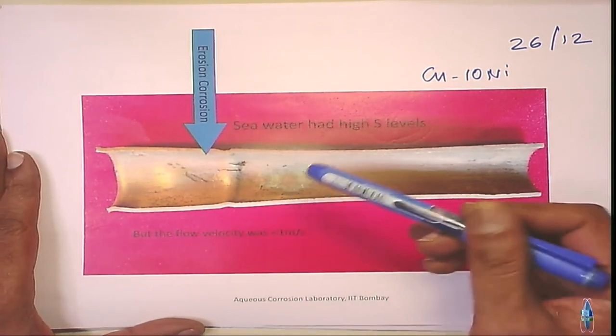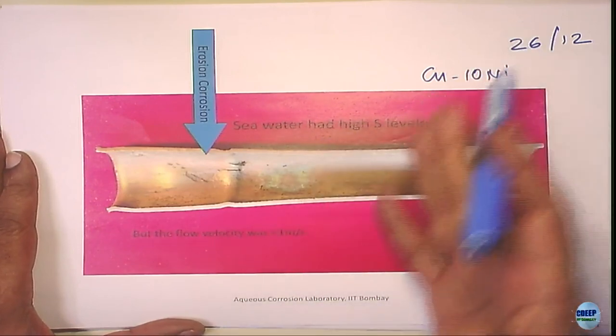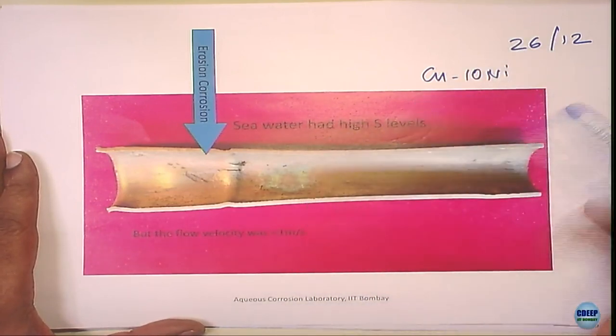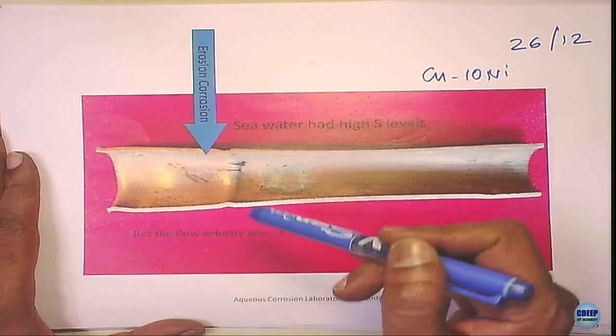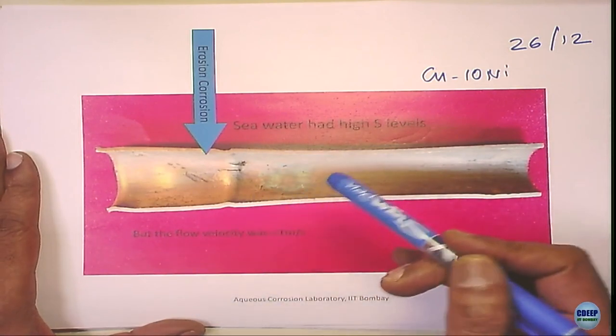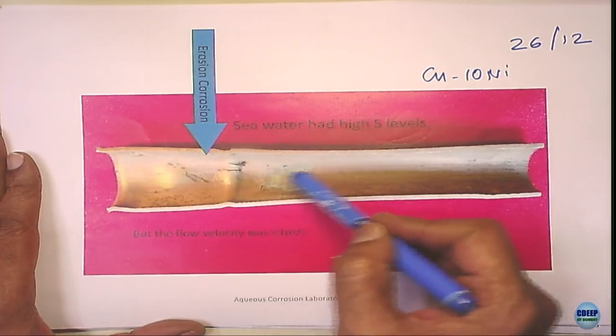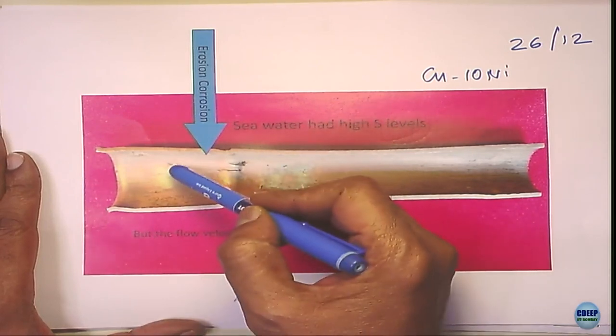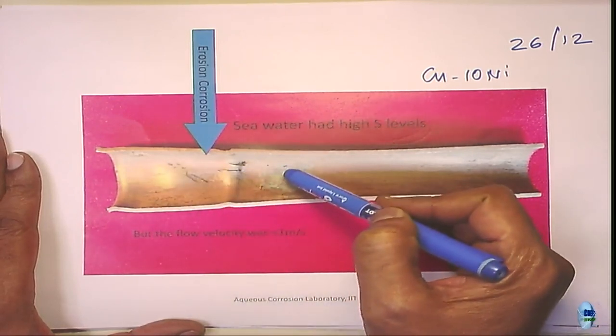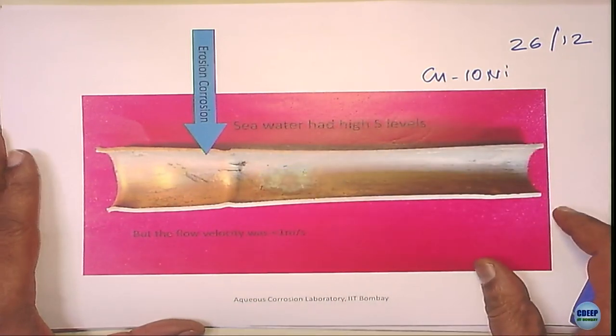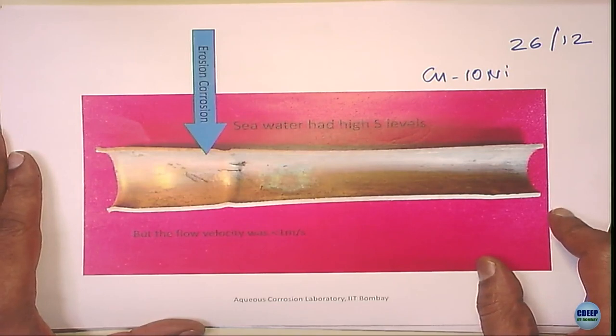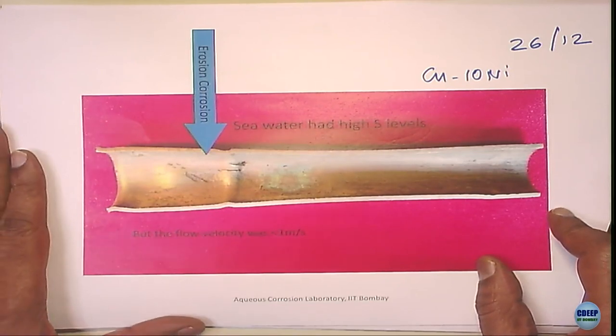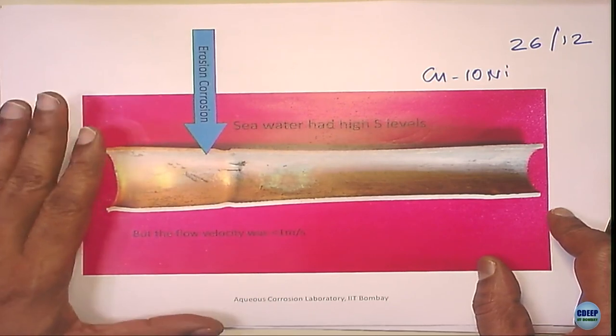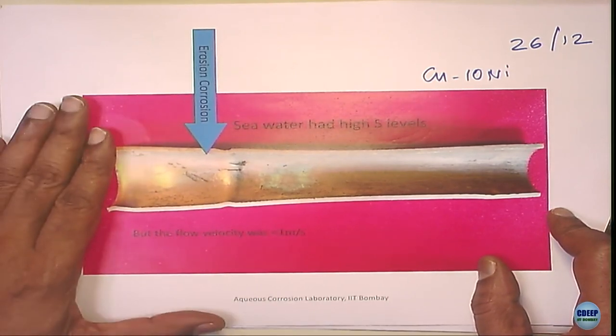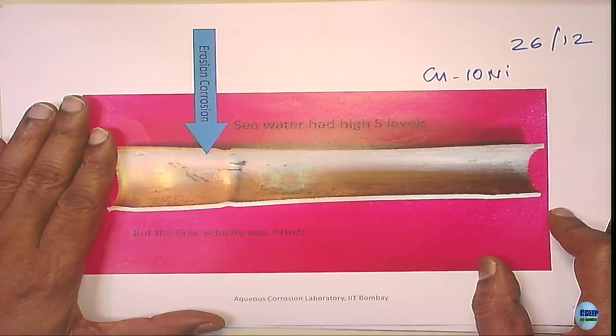See, two damage mechanisms are operating, no doubt about it. De-alloying is operating, but what is the primary or the faster damaging mechanism? The faster damaging mechanism, in my view, has been erosion corrosion damage assisted by these sand particles. So if you wrongly diagnose it, you have a problem. So finally, we went for higher nickel. Anyway, we convinced the people to go for nickel and the tube did not fail for 3 to 4 years, okay.